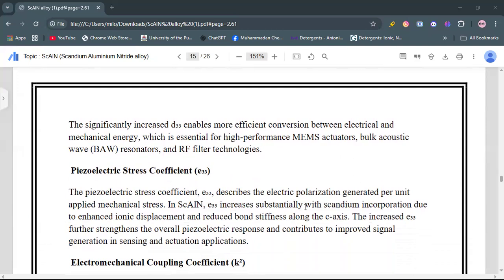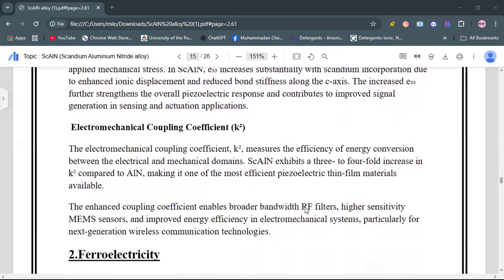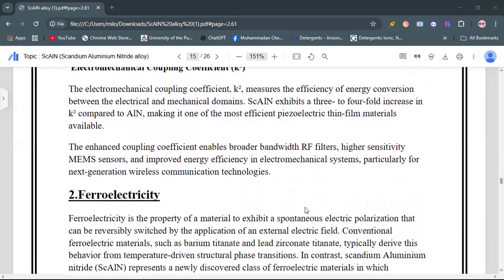Piezoelectric stress coefficient describes the electric polarization generated per unit applied mechanical stress. In scandium aluminum nitride, it increases substantially with scandium incorporation due to the enhanced ionic displacement and reduced bond stiffness along the c-axis. Electromechanical coupling measures the efficiency of energy conversion between the electrical and mechanical domains. Scandium aluminum nitride exhibits a 3 to 4-fold increase in electromechanical coupling coefficient as compared to pure aluminum nitride, making it one of the most efficient piezoelectric thin film materials available.